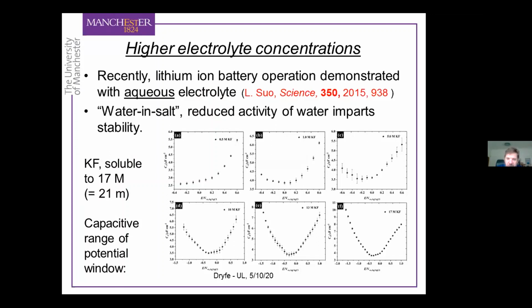The numbers might not be very clear, so I'll just talk you through them. Here we have the capacitance as a function of potential. This is for 0.5 molar KF. And then we're increasing as we go from left to right, and then in the second row as well, increasing the KF concentration. So this is 0.5 molar, this is 1 molar, this one on the right is 5 molar. Here we have, bottom left, 10 molar. Here we have 13 molar, and here we've gone up to the solubility limit. This is 17 molar. And you can see two things.